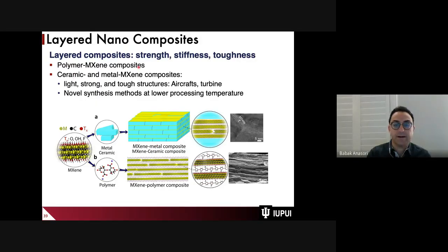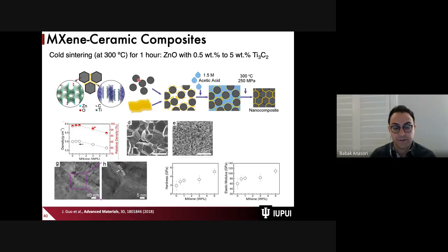For example, for ceramic MXene composites, this is research that we did at Drexel with collaborators at Pennsylvania State University, that showed that by mixing MXenes with zinc oxide, the 2D flake of MXene will go at the grain boundary of this oxide ceramic and wrap around these zinc oxide particles. Then by sintering only at 300 degrees C with 250 megapascal, we can get almost to 100, or slightly less, like 96% relative density of the composite.